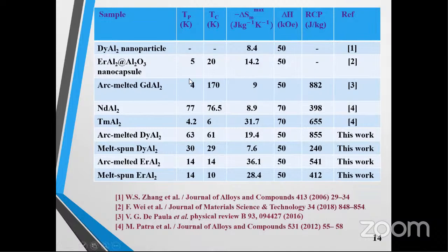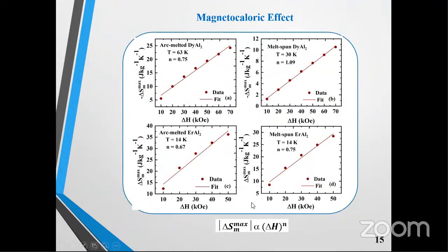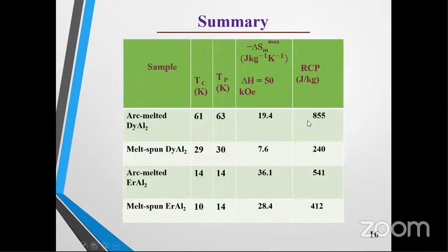And here I have listed the peak temperature where the negative of delta SM is maximum, the Curie temperature and the negative of maximum of change of magnetic entropy for different field values, and the relative cooling power of some of the samples. And this shows the dependence of change of magnetic entropy upon the change in magnetic field. And I have calculated the n values for these 4 samples. And so in the summary part, I have listed the Curie temperature, peak temperature, and the negative of maximum of delta SM and RCP values for 4 of my samples. And here you can see that for the Melt-spun DyAl2 and Melt-spun ErAl2 sample, the RCP has been reduced. Also the Curie temperature, which shows the formation of nano grains. Thank you.